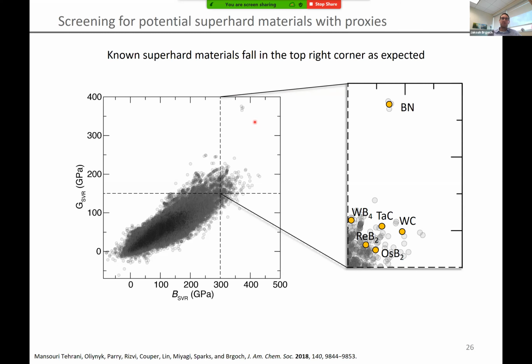This should not be that much of a surprise that boron nitride is its own impressive island, because boron nitride is really the only compound that's competitive with synthetic diamond. It's worth noting that on our screening here, we only have binaries and higher, so diamond's not present here. But boron nitride has been an industry standard material for the better part of 60 or 70 years, so it's not a surprise—it was discovered without needing anything like machine learning or computational development. It's simply just the best material available.